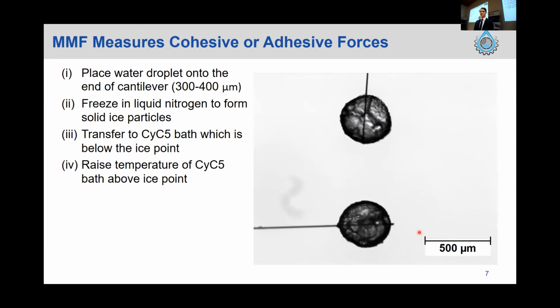So firstly, a hydrate particle was formed with these 4 steps. Firstly, the water droplet was sprayed onto the end of one of the cantilevers, about 300 to 400 micron diameter. And then that particle was transferred to liquid nitrogen, where it was allowed to freeze. And then once that particle had frozen, it was quickly transferred to the cyclopentane bath, which is pre-cooled below the ice point. And then once in the bath, that cyclopentane was raised to above 0 degrees, basically, where it's in that hydrate formation region of up to 7.7 degrees for cyclopentane.